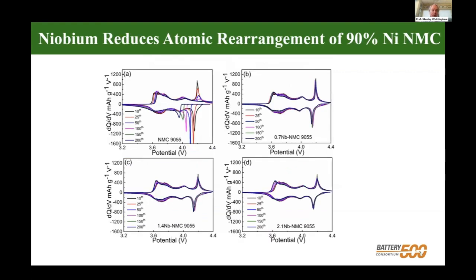If we now look at the capacity change with voltage, you can see exactly the same essential behavior. We look at this with no niobium, you can see these peaks are shifting the whole time, telling us we're changing the composition of the material. As soon as we get to higher niobium, even 0.7, we're not seeing any shifts of this peak. So the redox behavior is constant once you put a little bit of niobium into the lattice.